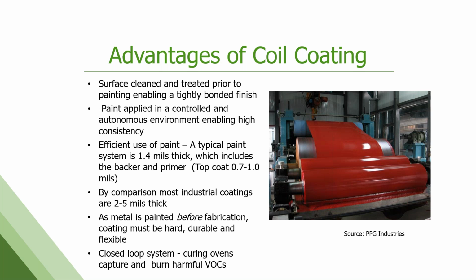So the substrate is cleaned and treated prior to the paint going on, and this all happens very quickly and in close succession to one another. So you get an incredibly great adhesion of the coating to the substrate. It's done in a very controlled manner, so we get great consistency from run to run, from batch to batch, from coil to coil. It's a very efficient process as well. We're using very little paint.